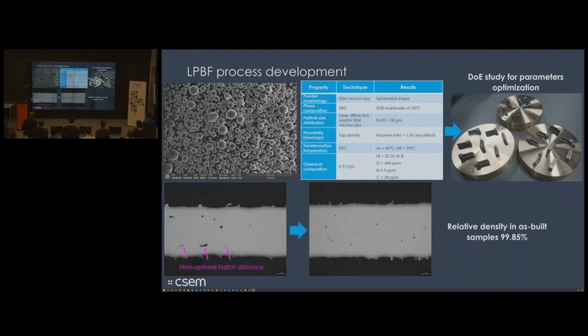For example, during the process, we do microstructural analysis. We've seen that in some promising recipes, we still had some non-optimal hatch distance. That's usually seen by observing lack of fusion defects that are aligned at certain points. And finally, we achieved parts with relative density in as-built samples higher than 99.85%. Of course, this could be even further improved, for example, using hot isostatic pressing, but it was good enough for our application.